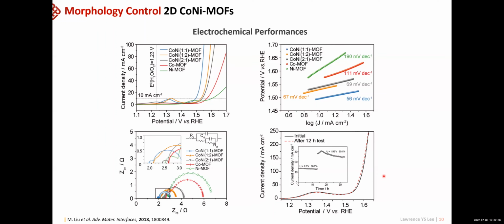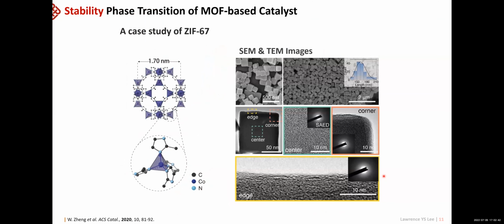So we start to question about their stability. So instead of complicated two-metal bimetallic MOF, we used another simpler type of MOF called ZIF-67. This is another type of MOF made of cobalt and imidazolate. The cobalt, as you can see from this picture, is tetrahedrally coordinated, and when we prepare the MOF, they give this nice cubic shape of crystal structures.